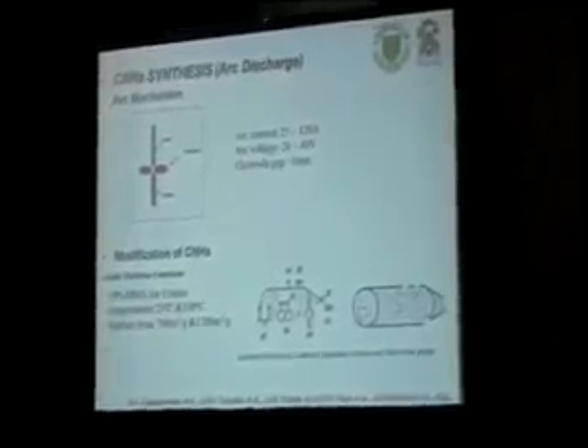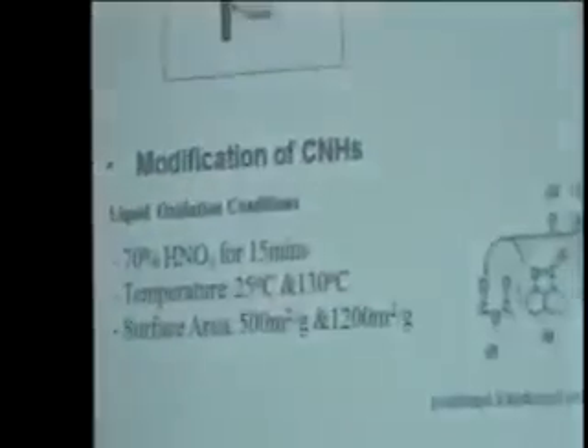Once the carbon nanotubes have been produced, modification of the surface properties could be done by liquid oxidation. The literature result shows that with 70% acid treatment for 15 minutes, the surface area improved from 500 to 1,200 at 25 degrees Celsius and 130 degrees Celsius. Modification introduced functional groups on the surface of the carbon nanotubes like carbonyl groups or carboxylic acid groups.